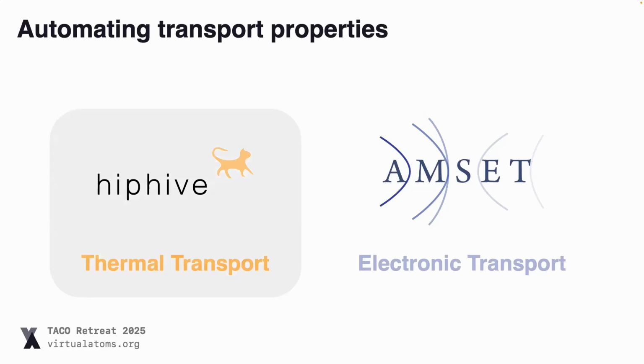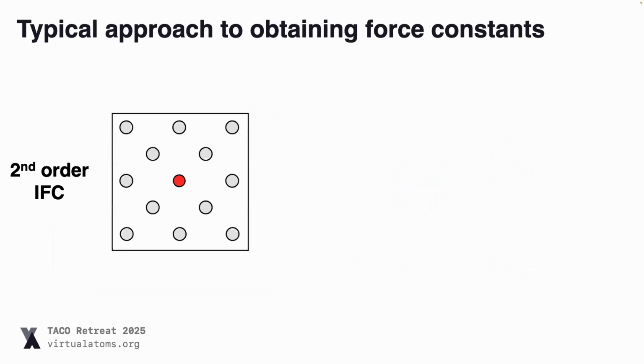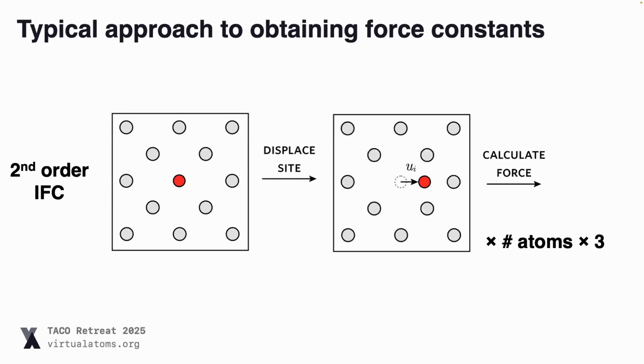And as this graphic shows, here we have not developed this code ourselves. We're using a package called hiphive to do a lot of the work. So some of you may have heard of that before, but I'll explain a little bit about what hiphive does. So the typical approach to obtaining force constants in materials, we take a cell, we then have to displace some atoms away from their ideal sites, and we calculate the forces on all of the atoms. We repeat this for every atom in the cell in all the directions. Obviously, you can reduce this by symmetry, but this allows us to obtain the second order force constants for a material.